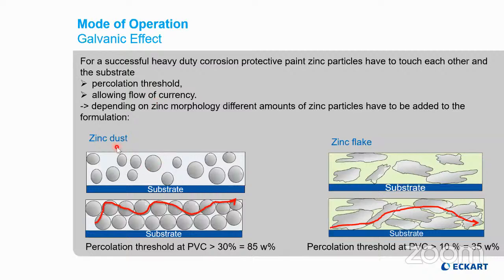That point where the individual zinc particles get in touch with each other is called the percolation threshold. And because zinc dust has a very low surface area, the loading of zinc dust into a formulation must be very high, meaning 85%, in order to generate the percolation threshold. With zinc flake, with the comparatively higher surface area, it is not necessary to load the formulation with that high amount of zinc flake particles.